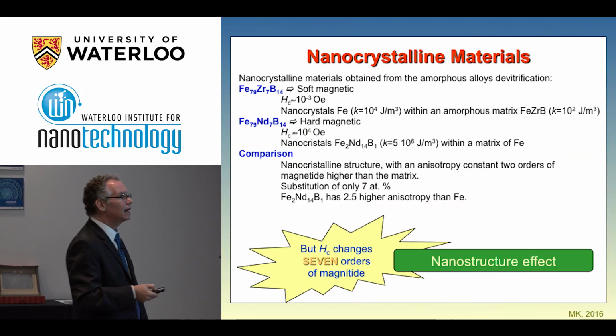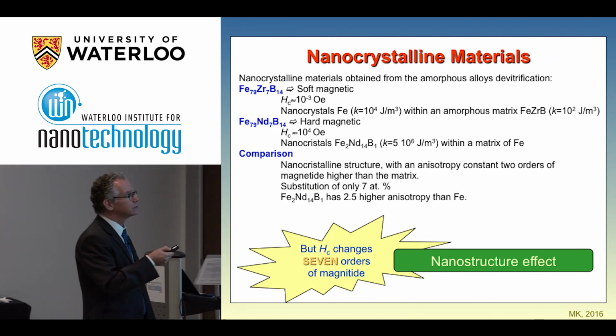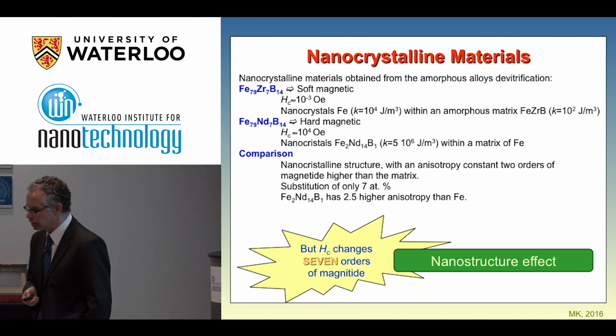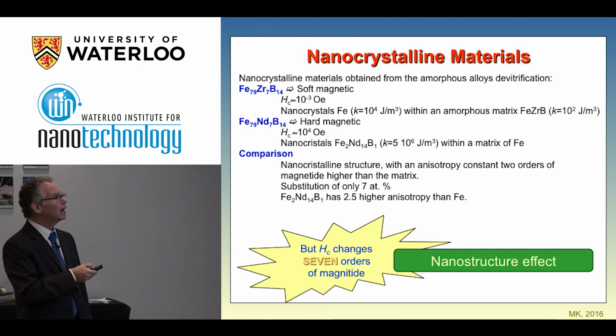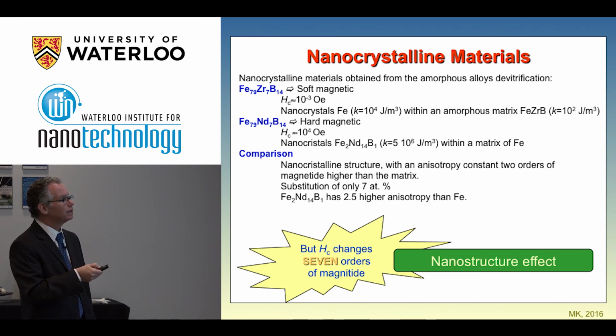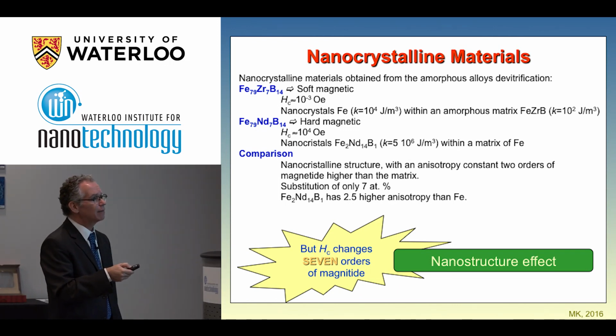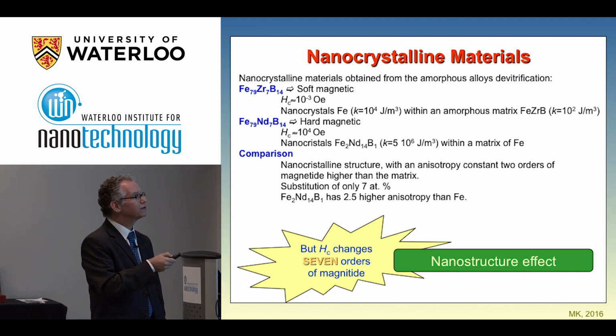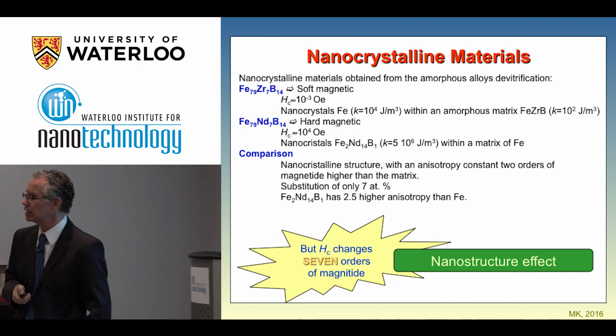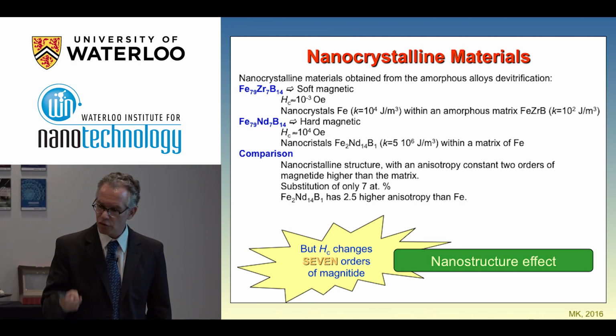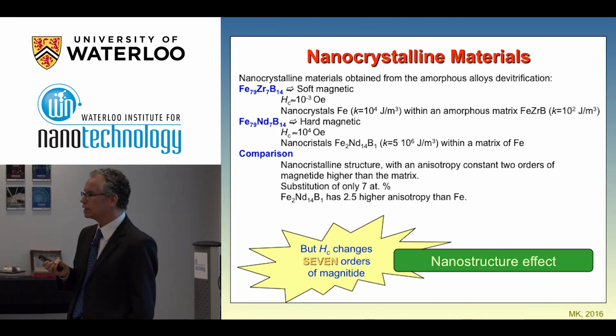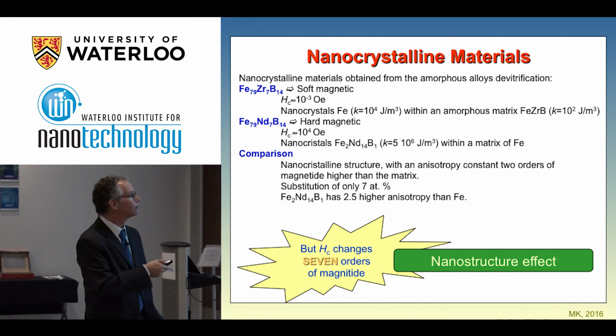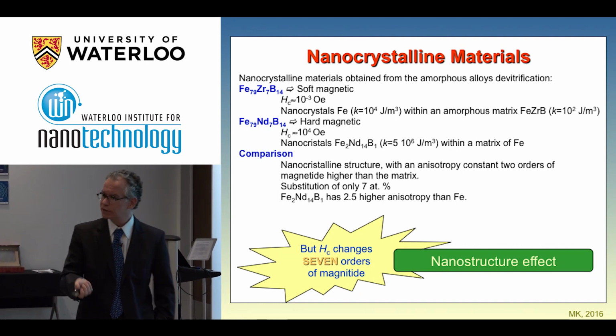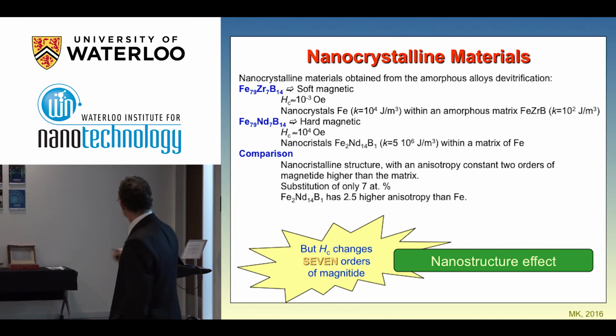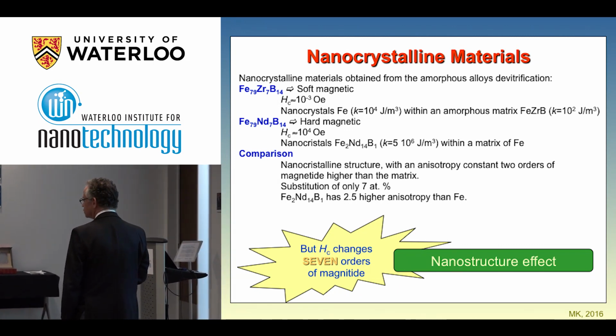So just to show you one interesting example, this kind of materials, these ones are produced by melt spinning. These materials are soft magnetic materials. They are nanocrystals of iron in an amorphous matrix. And these materials are among the softest materials that we have. So they are very good for transformers and any soft magnetic materials application. Sensors as well. So all kind of accelerator sensors, magnetic impedance sensors, a lot of sensors that you can work with this kind of soft magnetic materials.